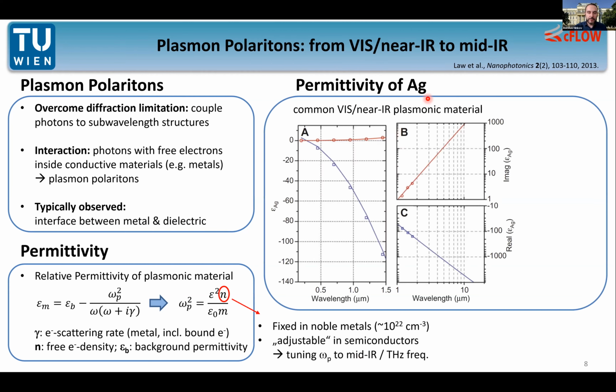But going back to the noble metals, we can see, for example, if you look at the permittivity of silver, you can see that in the visible to near-infrared spectral range, this left plot here, the real part of the permittivity is negative. So far, so good, that's normal. And if you look at the values, they are basically on the same order as for dielectric materials that we have in this wavelength range. So this situation leads to the fact that we can have this sub-wavelength confinement in visible and near-infrared spectral range. The situation becomes completely different if we move on to the mid-infrared spectral range.